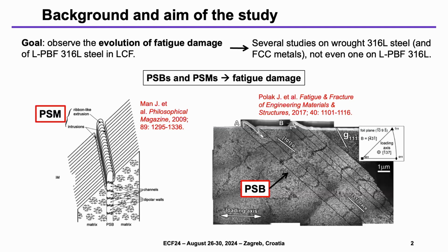In the past decades, many studies focused on the role of the so-called persistent slip bands and persistent slip marks in fatigue damage. Basically, the persistent slip bands are regions of material where strain localizes during cyclic loading. And when these bands intersect the free surface of the material, they create extrusions and sometimes also intrusions, which then appear as marks on the free surface. And the intrusions are related to crack initiation sometimes.